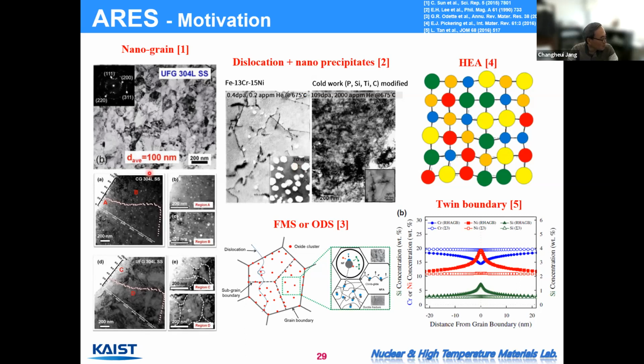There are several different methods, but for the formation of nanograins, you need severe plastic deformation, which is not very practical for large components. The dislocation and nanoparticle approaches have some advantages, but they also have limitations. And for the FMS alloys, the ferritic martensitic steels and the ODS alloys, it's good, but ODS fabrication also has fabrication issues. High-entropy alloys and twin boundaries are currently at a very early stage of development.